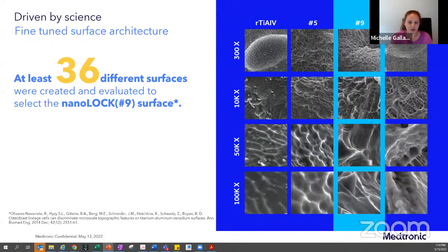So we didn't stumble upon the Nanolock technology right away. We tried testing different combinations of grit blasting and acid etching to produce different surfaces to mimic that bone remodeling process. A little over 36 different surfaces were looked at visually with SEM, and then we narrowed that down to three surfaces to evaluate in cell culture and see how cells would respond. If you look to the right, there are images of the different surfaces.